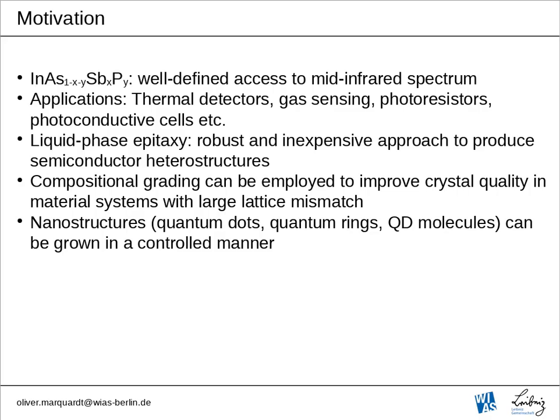The systems I am talking about today have been grown using liquid phase epitaxy, which is a robust and inexpensive approach to produce semiconductor heterostructures in surprisingly good crystal quality. A particular strength of liquid phase epitaxy is that one can introduce on purpose a composition gradient within the heterostructure, which is very useful to significantly improve the crystal quality, in particular in material systems that exhibit a large lattice mismatch. We have also seen in the past that nanostructures such as quantum dots, quantum rings, even quantum dot molecules can be grown in a controlled manner using liquid phase epitaxy.